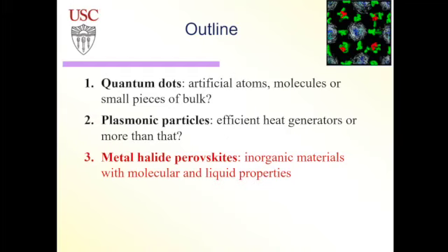In the physics community, this would be polaron, but this polaron formation is different from polarons in normal semiconductors, which are very small polarons. This is a very large polaron. You have very large scale distortion of your lattice and rearrangement of this molecule inside the lattice. So it's quite different from normal, typical TiO2 or silicon semiconductors.